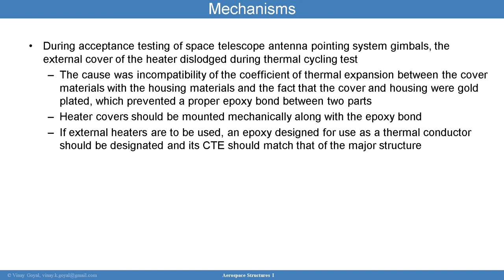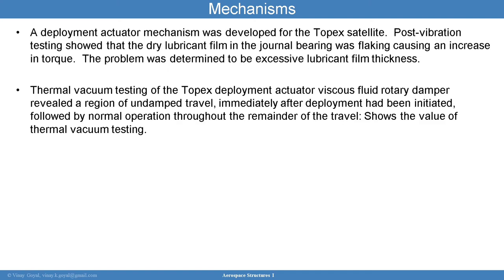Heat cover should be mounted mechanically along with an epoxy bond. That's going to help a little bit with this CTE issue. If external heaters are to be used, an epoxy should be designed for use as a thermal conductor so that CTE mismatch is minimized. We also want to pay attention to issues with deployment actuator mechanism, which was really, one